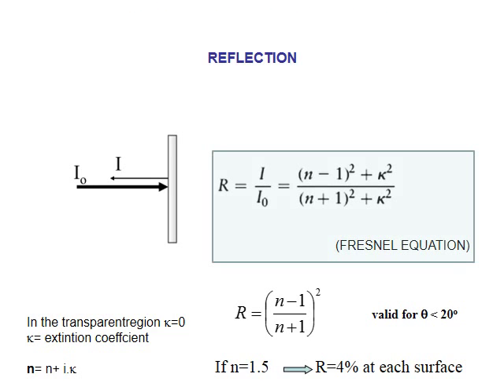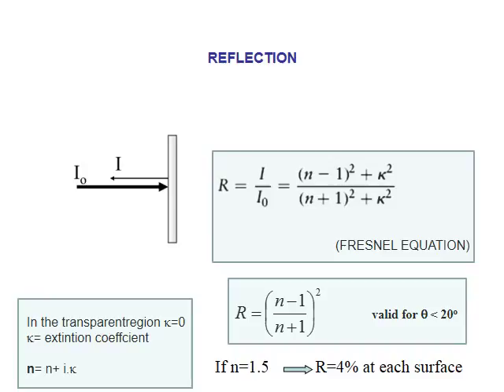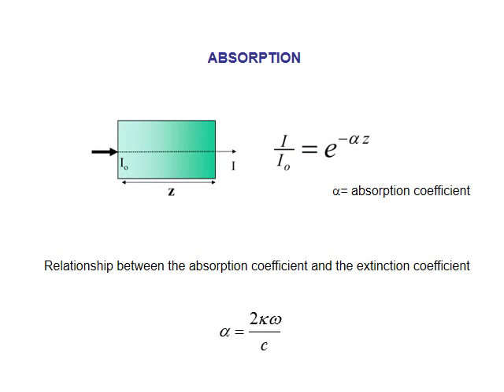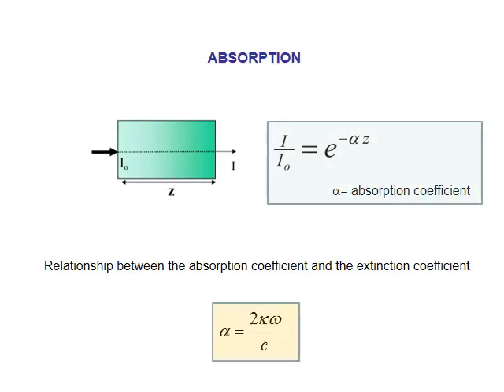Reflection will be given by the Fresnel equation, which takes into account the refractive index and the extinction coefficient. In the transparent region, the extinction coefficient is zero, and therefore the refractive index is given by this expression. The reflection will be given for low angles by this simple relationship. It means that if the refractive index is around 1.5, the reflection at each surface will be around 4%. Absorption will decrease exponentially with z, the optical path, and the absorption coefficient, alpha. The relationship between the absorption coefficient and the extinction coefficient is given by this expression.